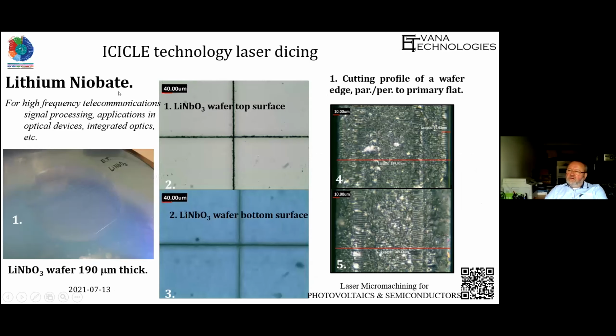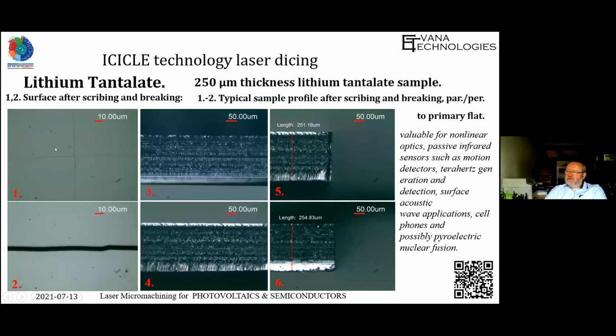Here you have lithium niobate. It's used for telecommunication devices, material applications, optical devices and integrated optical schemes. We made some trials for this very fragile and brittle material, and we get good results for this scribing and breaking, meaning dicing, and our results really overcome other competitors. Again, a nice surface view after scribing, and the cross section is also quite good.